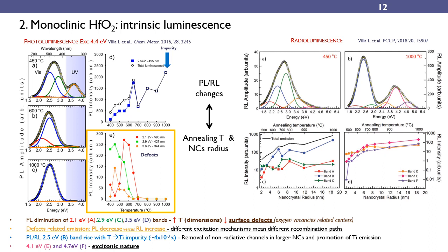If we want to understand the origin of the blue band, we must take into account the results obtained by exciting with ionizing radiation. In fact, in radioluminescence, we find the same bands as in photoluminescence, plus 2 additional ones in the UV that have been attributed to excitons. In radioluminescence, all the bands increase.